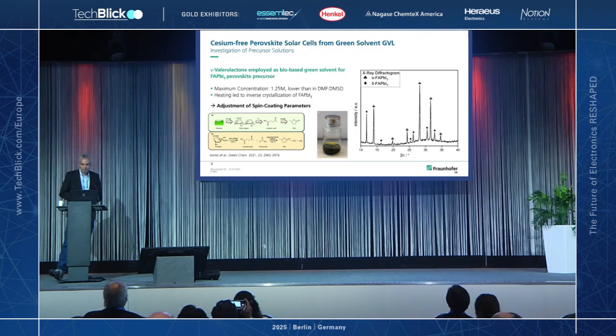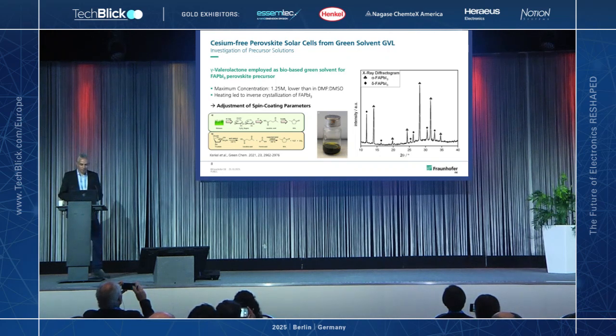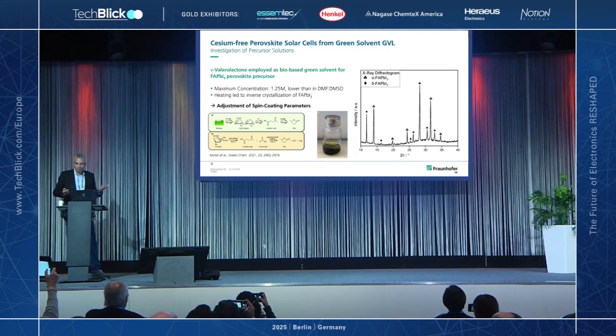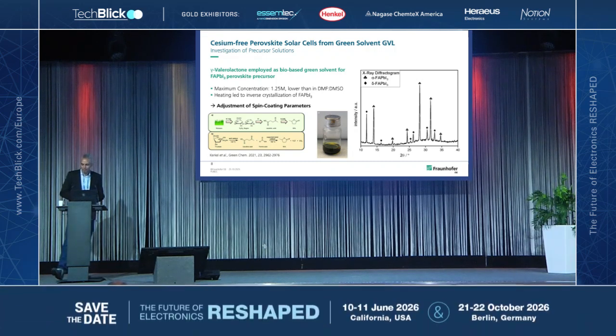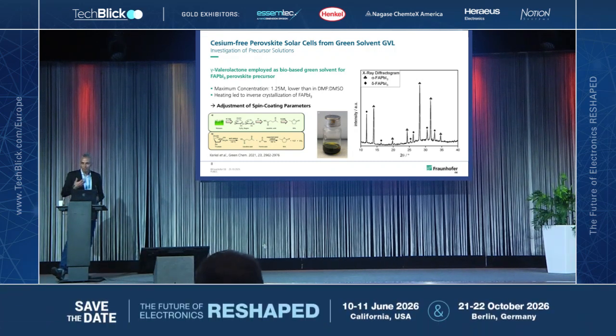And when we started to work on this, we found that the maximum concentration of the precursor materials we use is significantly lower than in typical solvents like DMF and DMSO. And then we, of course, started thinking how can we increase it to have the same layer thickness and so on. And, of course, one logical thing or first thing which you could think about is heating the solution. This, however, did not lead to any result that we expected, because instead of increasing the solubility, we found a precipitation of a black material, and of course this black material turned out to be the perovskite, which was analyzed by XRD. And we could find that we really have this inverse